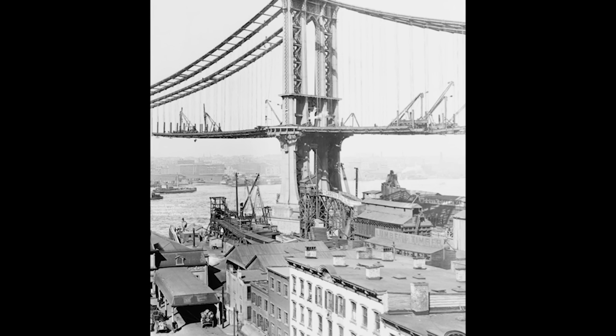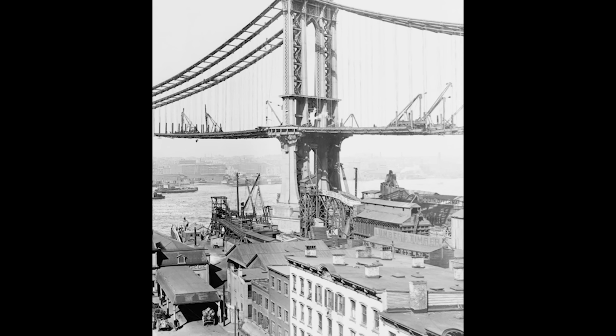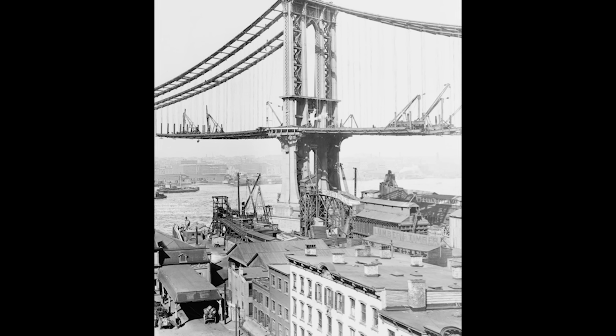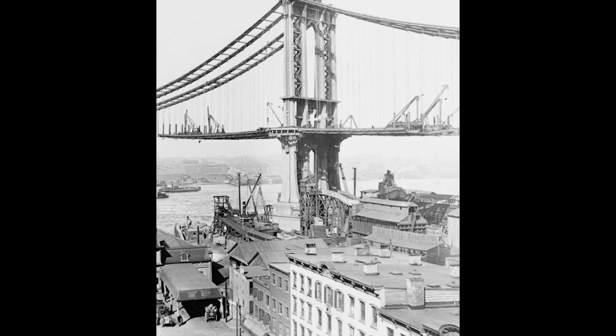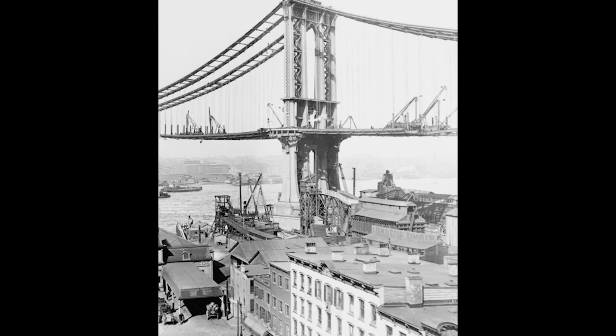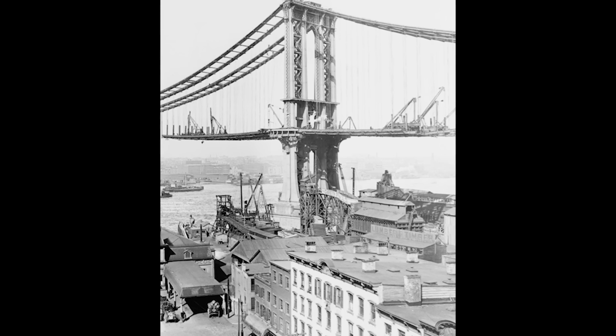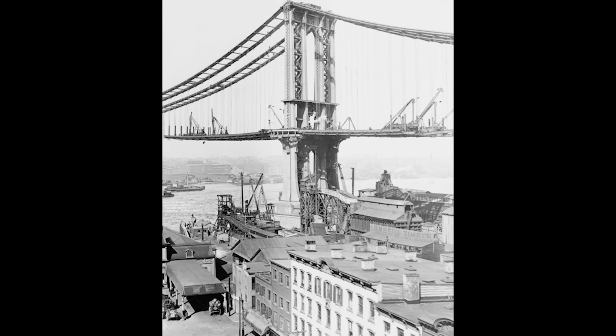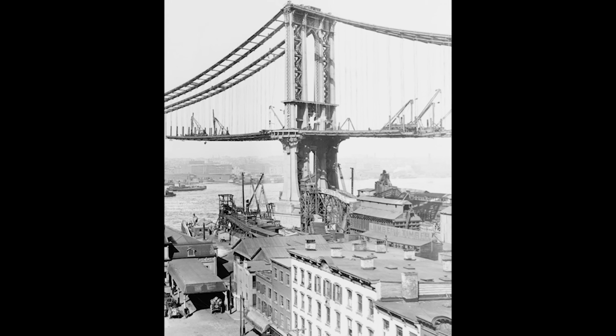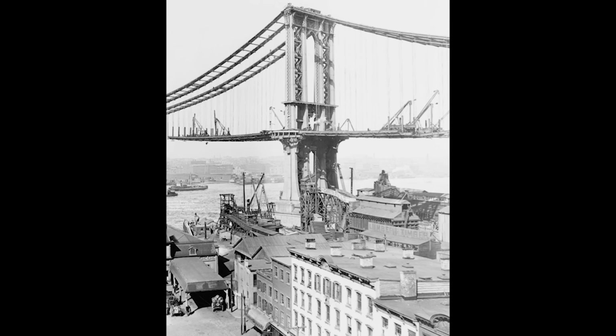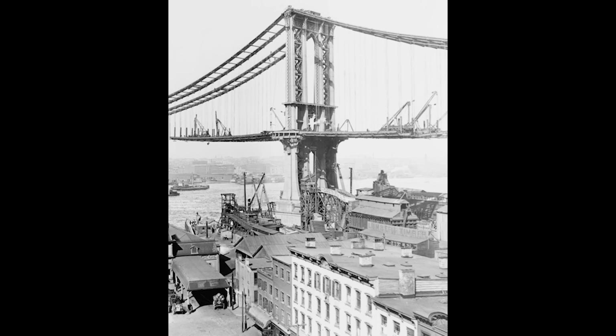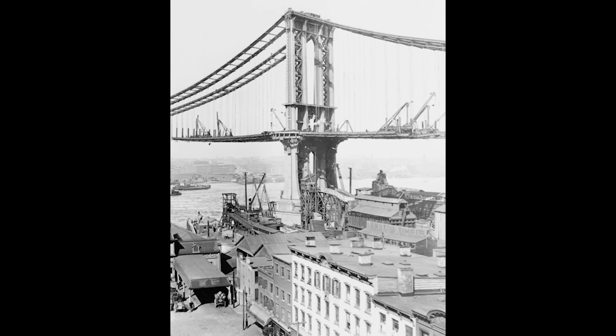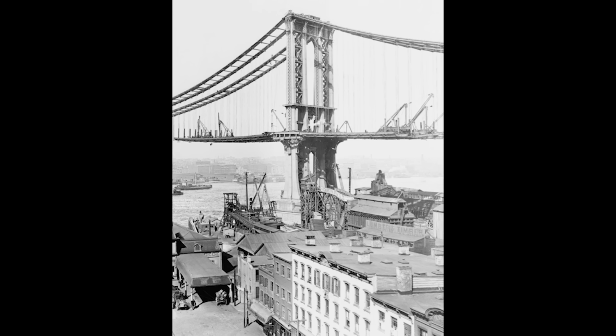High humidity prevented proper paint curing, while low temperatures made the red lead paste difficult to work and reduced paint flow characteristics. Wind could contaminate wet paint surfaces with dust and debris, creating weak spots where corrosion could begin prematurely. The work crews monitored atmospheric conditions constantly, adjusting their techniques or suspending operations when conditions threatened coating quality.